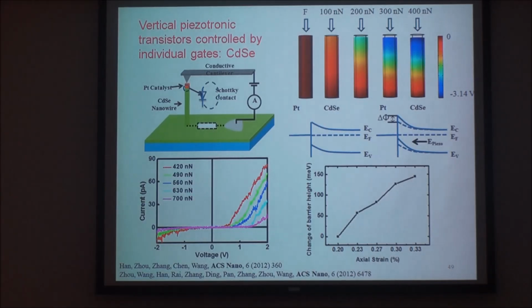Recently we not only make lateral devices, we also make vertical ones. The first one is done by AFM. You can put the AFM here and apply the mechanical strain step by step. The piezo potential increases, and this moves the IV curve to a higher turn-on voltage. So this uses the piezo potential to shift the turn-on voltage to a different value, with the strain applied here. Here there are 2 leads,